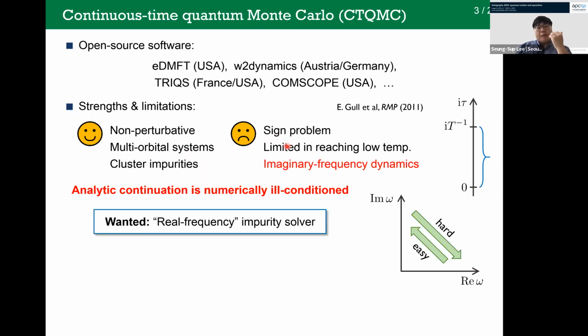First of all, it is a Monte Carlo method, so there can be a sign problem. When the sign problem happens, the Monte Carlo sampling does not converge. It actually happens for general parameters, because typically one can suppress the sign problem only for specific cases. So the Monte Carlo calculations become unreliable. And it simulates the correlation functions on the imaginary time axis. So the computation cost for simulating them increases quickly as one goes to lower temperature, because this simulation time interval increases with the inverse of temperature. And it works on the imaginary time axis.